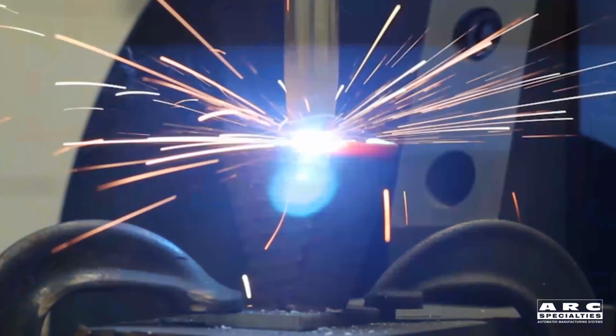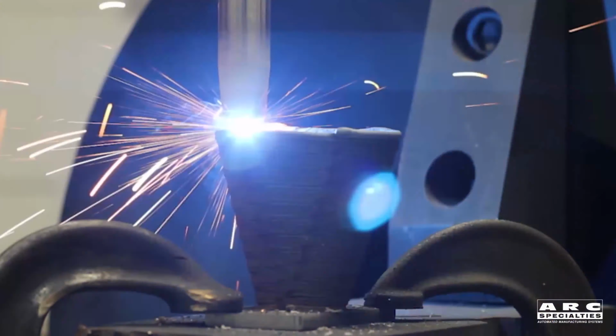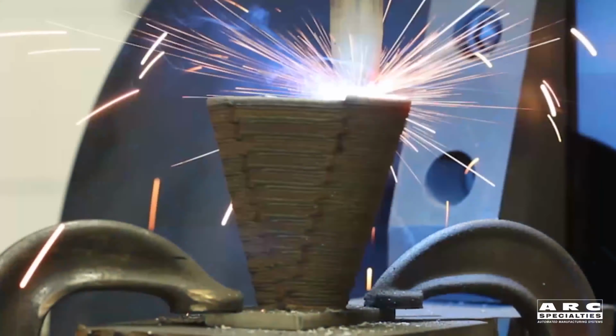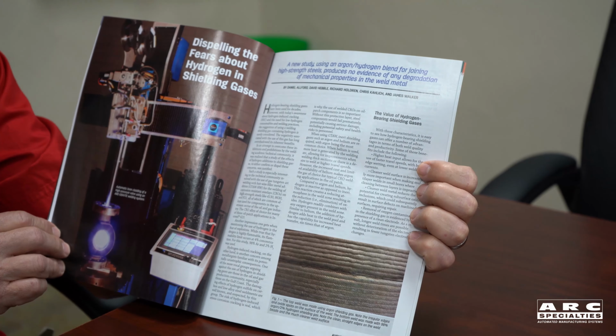But I've used in the past copper platens, water-cooled copper platens, as well as air blasts to increase the cool down rate. And so what we're doing is we're building upon some research we did back in 2017. That paper is available on our website as a white paper. It's also kind of a synopsis of it was published in the Welding Journal in August of 2017. What we did was we did a lot of work confirming that we did not degrade any mechanical properties of the base metal with the use of hydrogen.